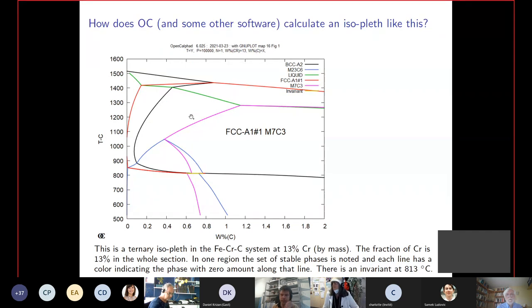I will take this iron chromium carbon system, and this is an isoplet where I calculate with 13% chromium and varying carbon content and the temperature. So in this diagram, you can only see which phases are stable in each region. So here you have liquid, here you would have liquid and FCC, here you have FCC and M7, and there is a very small three-phase region in between here, where the M7 carbide becomes stable. This is a single phase region, and this was also a single phase region. So here you can see the composition of the FCC phase in equilibrium with one other phase. But in this region, you don't know the amounts of the phases, you don't know chemical potentials or anything, but it gives you an overview, a kind of map of the diagram.